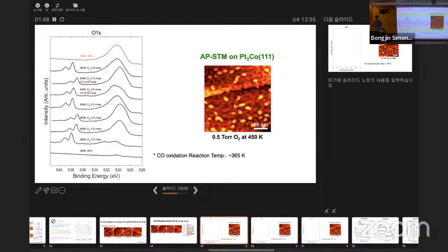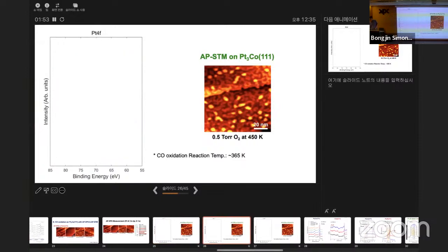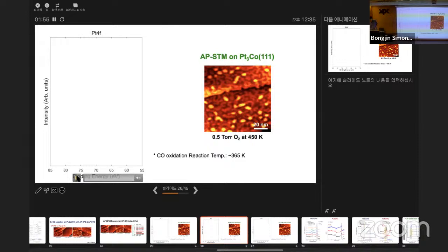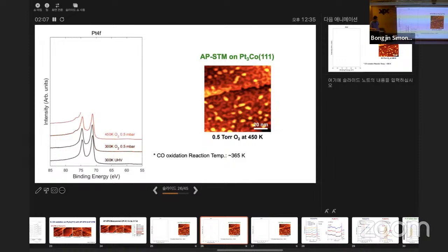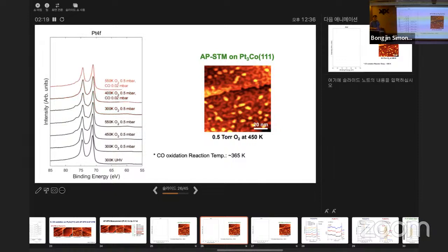But the thing is, when we actually look at the platinum, we did exactly the same steps. So we introduced 500 millitorr of oxygen. We look at the platinum 4f, and at about this pressure we start to see a shoulder on the platinum 4f, which we didn't see in platinum nickel. And platinum cobalt is clearly different.